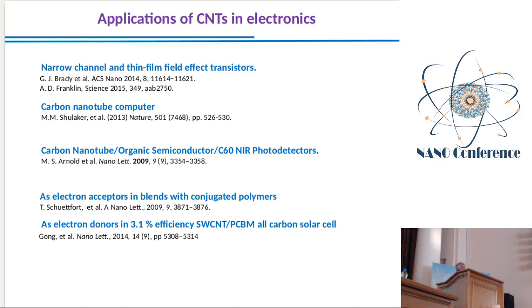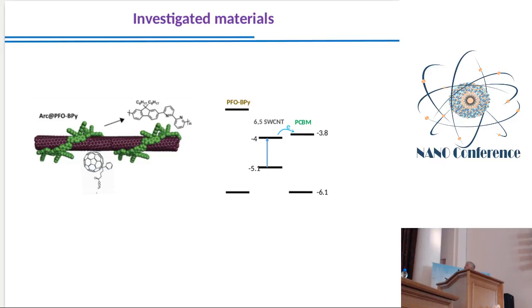Okay, so in our investigations, we use just one type of carbon nanotubes. It's 6-5 single-wall carbon nanotubes, where 6 and 5 define the symmetry of these carbon nanotubes. Usually after synthesis, a mixture of different carbon nanotubes is obtained, and particular species of carbon nanotubes can be separated by using conjugated polymers. As shown here, these conjugated polymers wrap around particular carbon nanotubes, and then these nanotubes become soluble, and you can separate them from other carbon nanotubes which remain non-soluble.